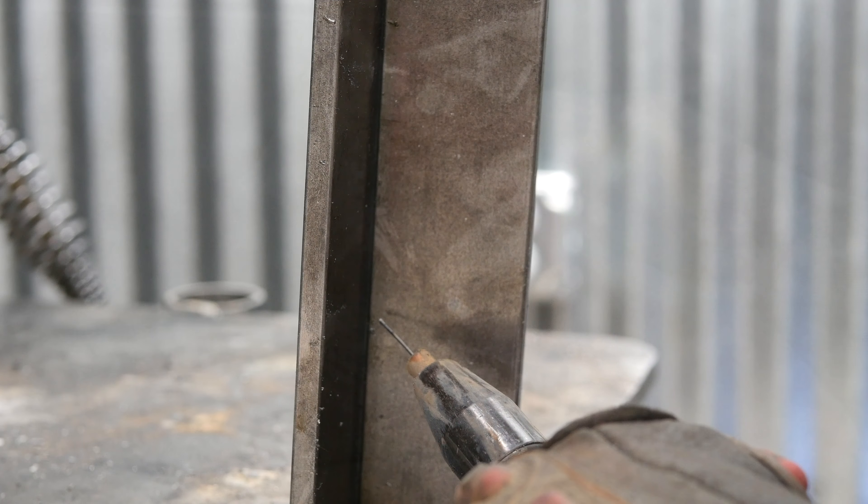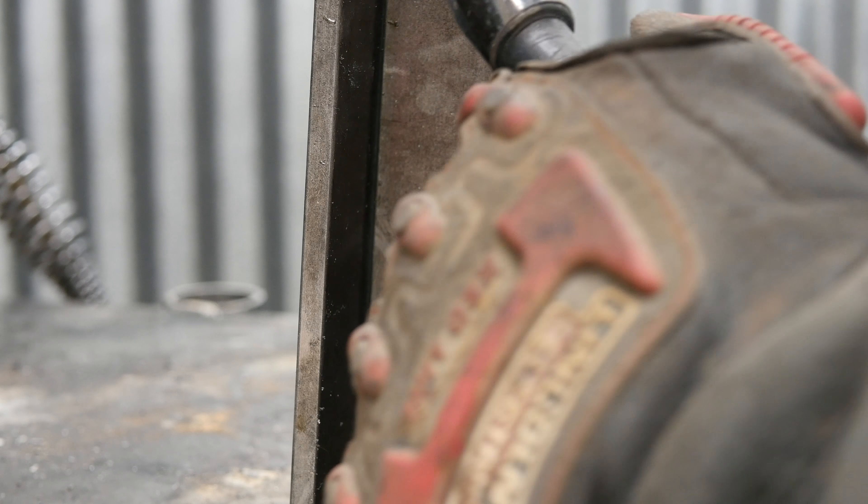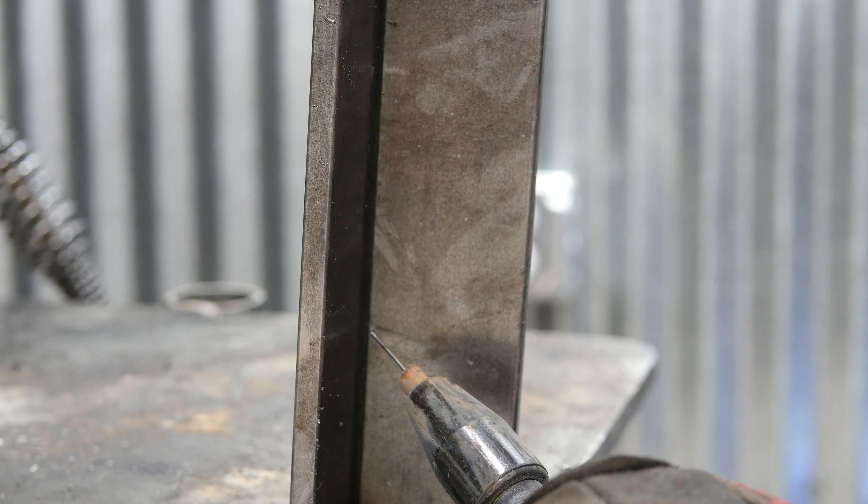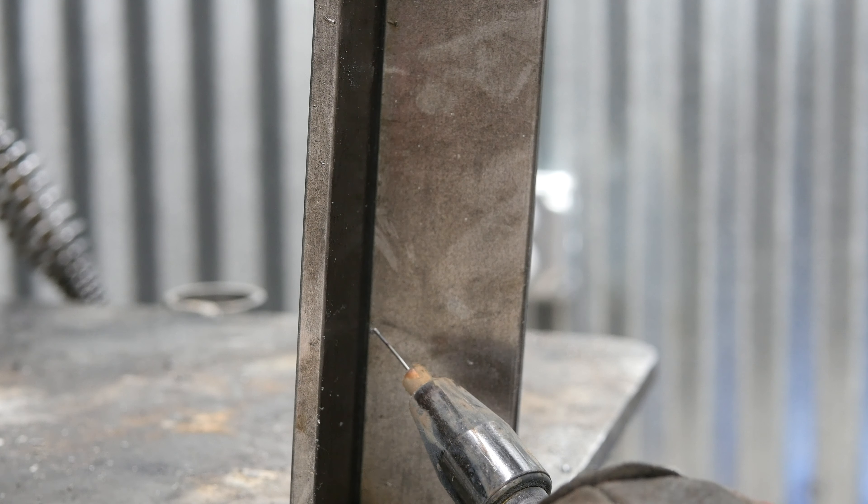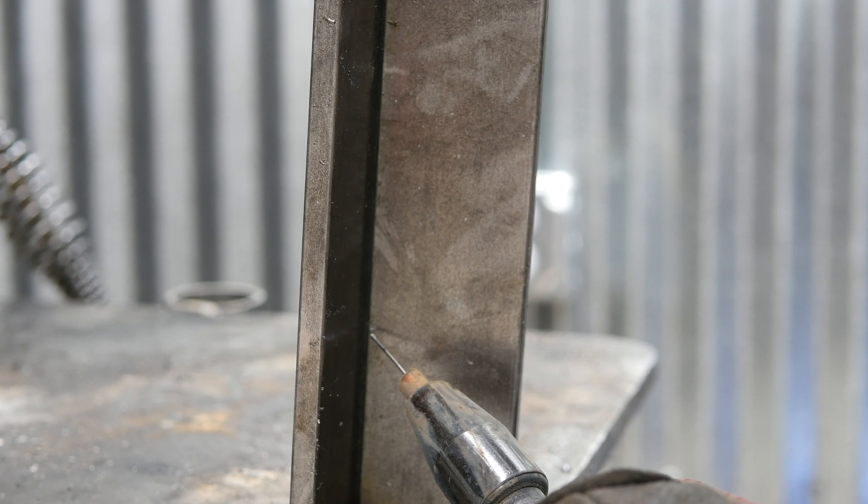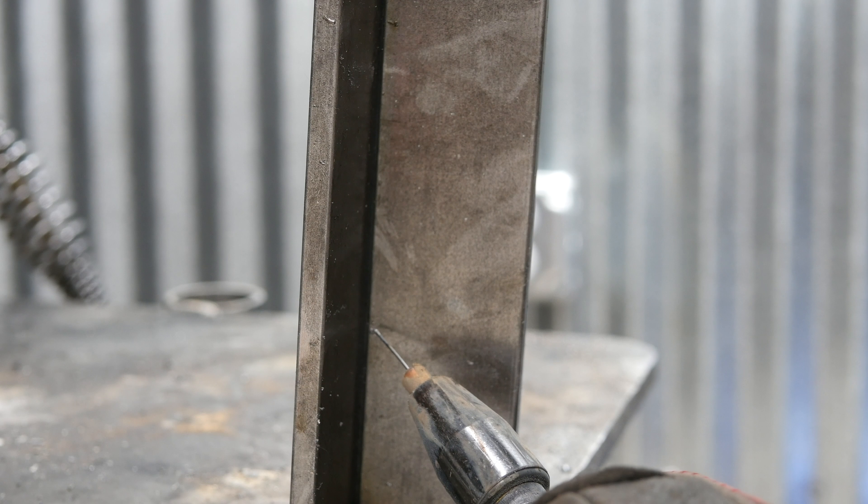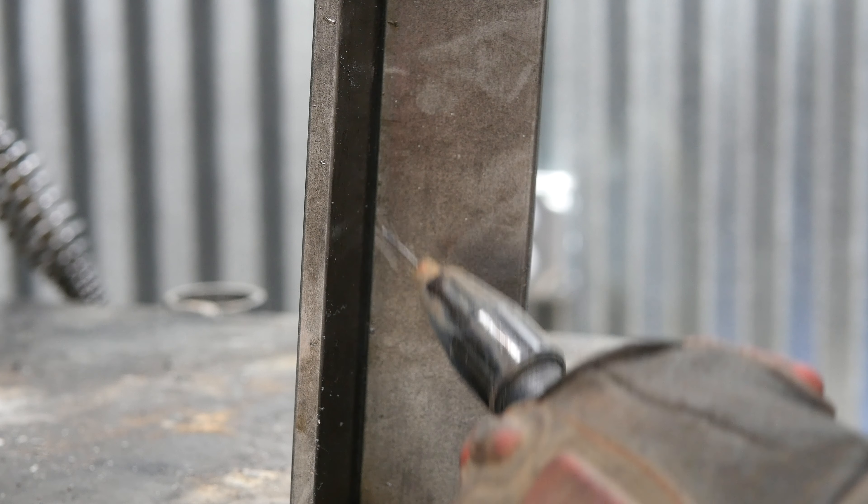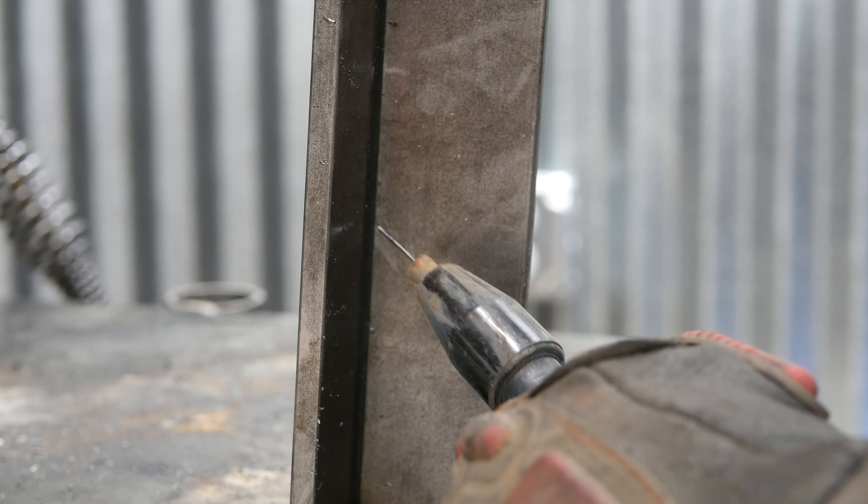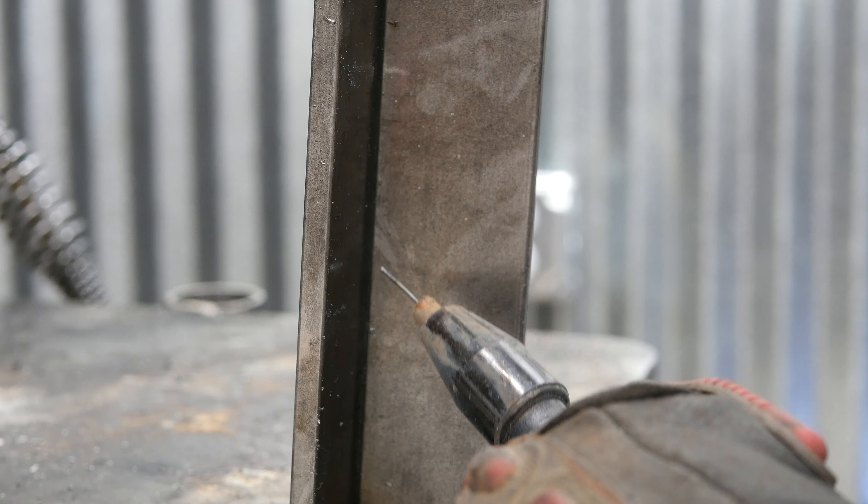So as I stated, we don't want to go vertical down with our wire. We want to go vertical up, especially when we're on thick pieces like this. We want to point the wire uphill, and when we strike the arc there's going to be a little slag shelf that's going to follow our puddle all the way up. You don't want to go so fast as to outpace that slag shelf because it's holding the puddle, or go so slow that you disrupt that little shelf and then the puddle falls out.